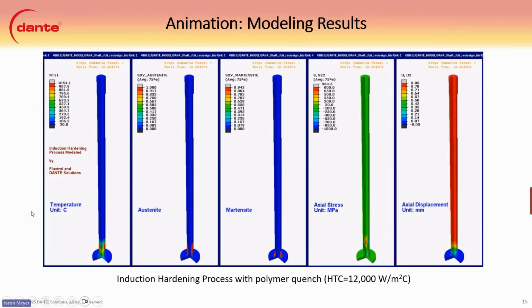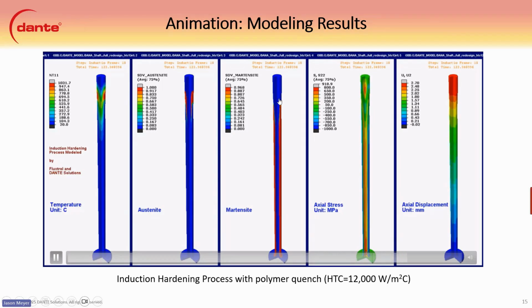And here we have a model of the contours, left to right. We have the temperature, and we can see where the inductor is with the red spot, where it's heating that temperature to above 1,000 degrees. And then about an inch afterwards, it's being quenched, and you can see that with the blue here. You can see the austenite phase being developed as it gets heated up properly. And then the martensite phase trails behind it, and you can see that's left over as it scans up the process. You can also notice there is some compression on the surface, and then there is some tension leading and trailing the inductor. And the axial displacement is shown at the end here as well. The big thing is really these stresses, the compression on the surface, and then the subsequent tension in the core.